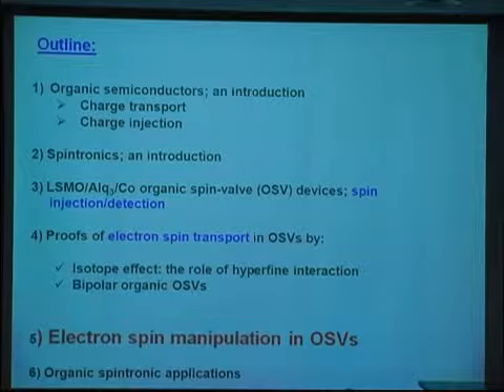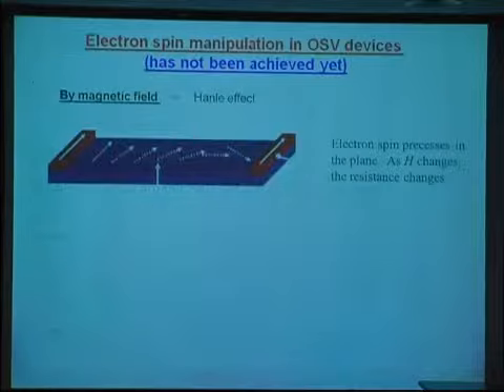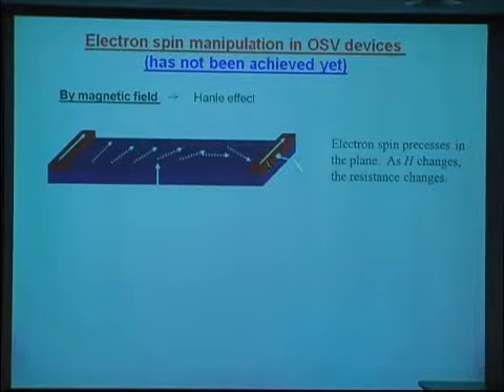Okay, so now I would like to go quickly through the spin manipulation in organic spin valves. Okay, so this is, like I told you, the horizontal structure for the organic spin valves or spin valves in general. One electrode we use to inject the spin aligned carriers and the other one to detect them. And now if you apply the magnetic field perpendicular to the spin, the spin precesses around the perpendicular field here. As a result, you change the resistance of the device.